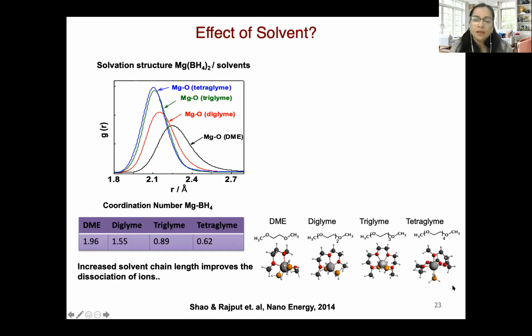Okay. And we learned that as we are increasing the chain length of Glymes, there is an increase in the magnesium solvent interaction. And this increase in magnesium solvent interaction results in a decrease of magnesium cation interaction, magnesium anion interaction, where the coordination number of magnesium and anion decreases from the range of being in aggregates all the way up to solvent separated ion pairs.